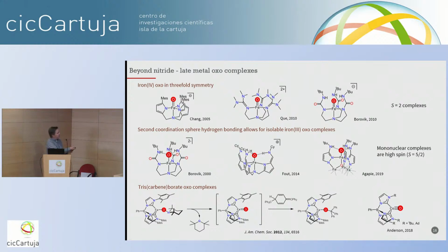Some time back, we showed that this tempo complex, which I showed earlier, if you heat it up, would eliminate an aminyl radical that just reacted with solvent. Generally, we believed it was an iron oxo that could be trapped, for example, with the trityl radical to make this alkoxide complex. And so we knew that most likely we could form an iron oxo, but we just had to figure out how to get to there.